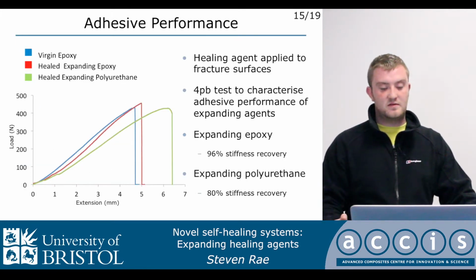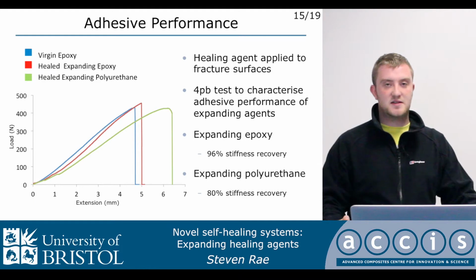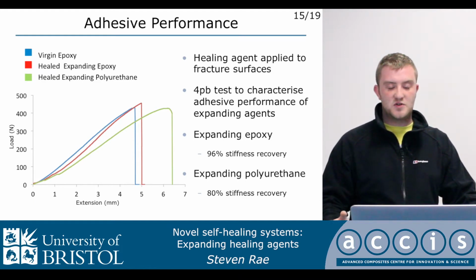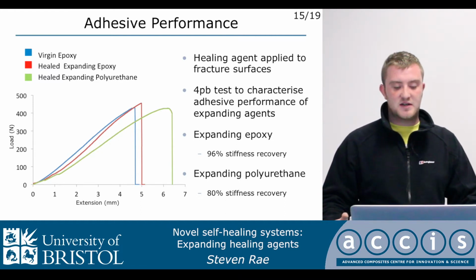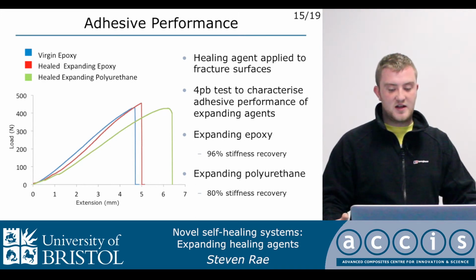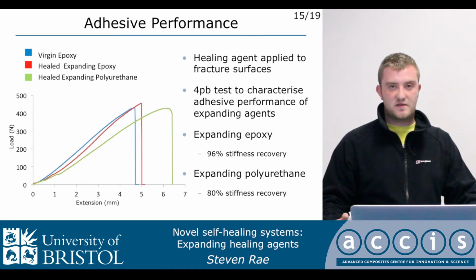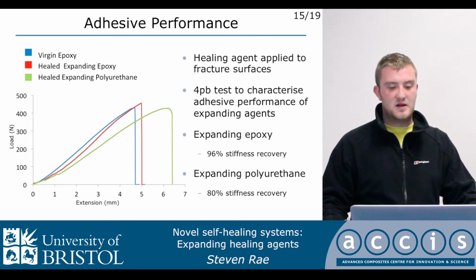So to test these, the epoxy system and the polyurethane system, we used them to repair an already failed epoxy block and then compared the stiffnesses after we tested it again. As you can see from the graph, using the epoxy system we get a very close match to the same stiffness as the virgin sample. And again with the polyurethane system, it's a high stiffness recovery, but as expected a bit more elastic due to the viscoelastic nature of the polyurethane. But this could be an advantage in fatigue performance for healed samples.